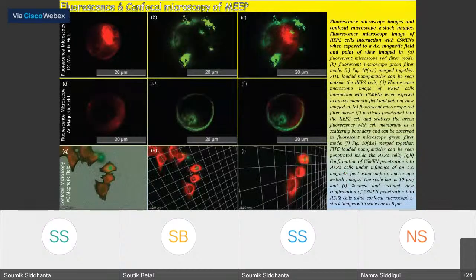This experiment was performed in an in vitro setup where we stained the cell cytoplasm with a red dye and the robots with a green dye. When we apply a DC magnetic field of particular amplitude, we can see that the robots are all present on the outside vicinity of the cell, whereas when we apply an AC magnetic field of modulated amplitude and frequency, we can see that these nano structures permeate inside the cell membrane, using the cell membrane as a scattering boundary.